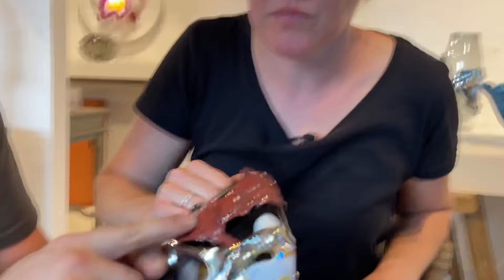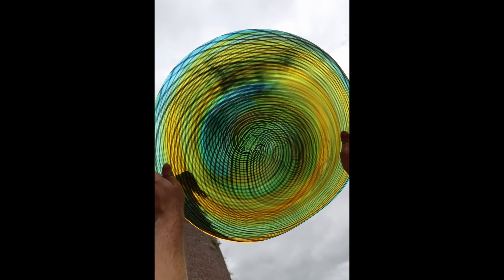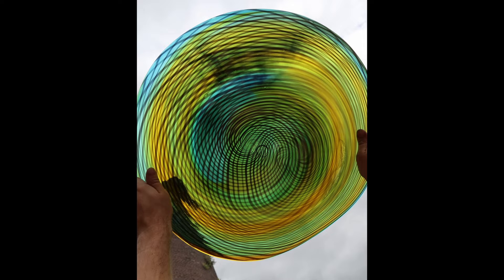That's copper ruby — that's how Bethany wants it, but technically it should be a transparent copper ruby. It's very specific in the way you treat the colour. And greens — for a stained glass conservator there are basically endless nuances in a green tint. You can have a whole rack full of green tints and still not find the right one. It might be okay through transmitted light, but then you apply paint and another very subtle, different paint, and it changes the colour of the glass based on what it's sitting beside.